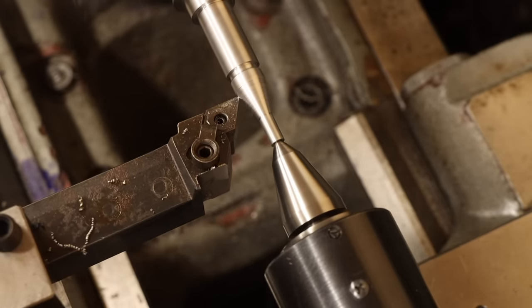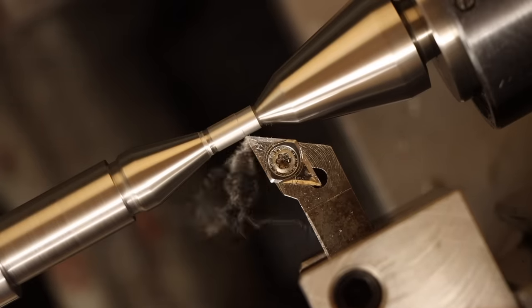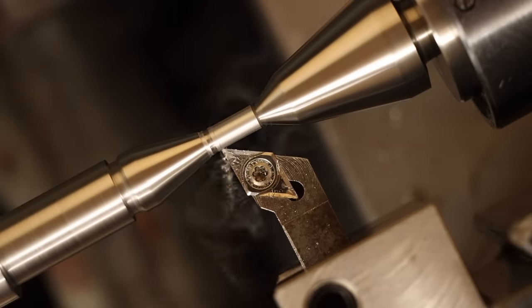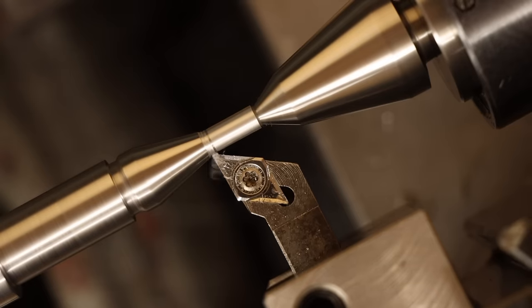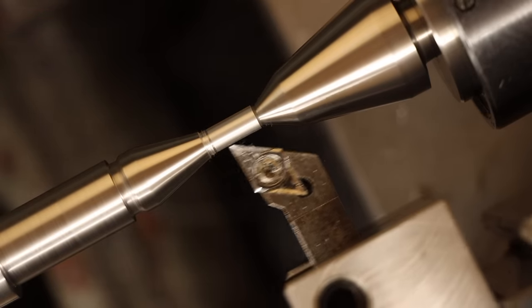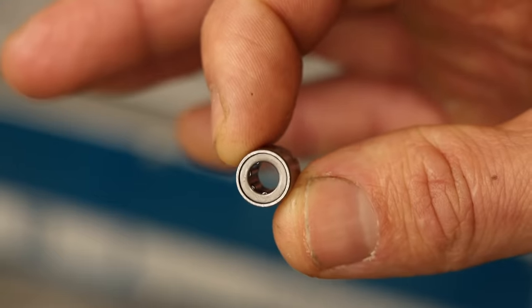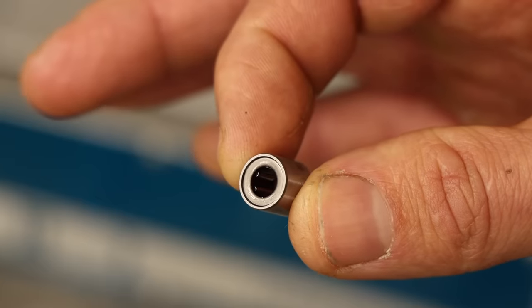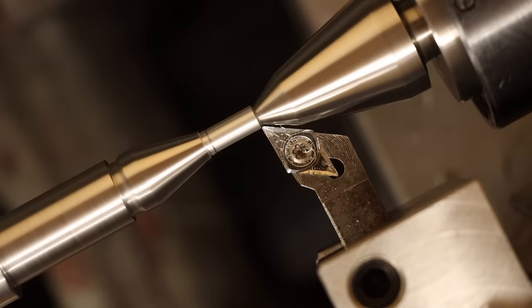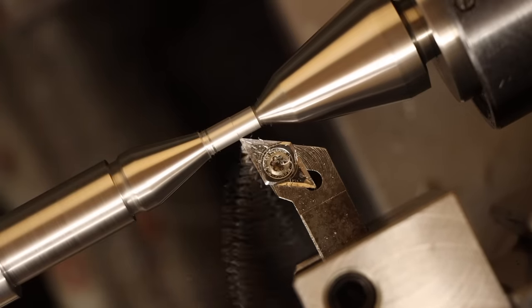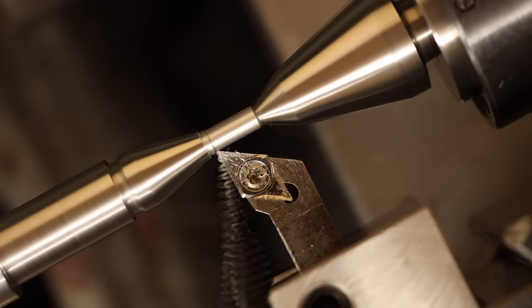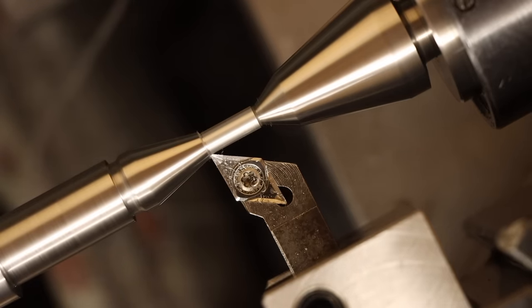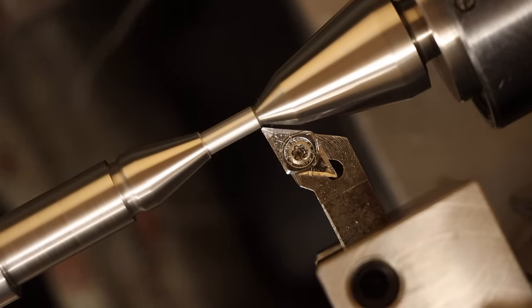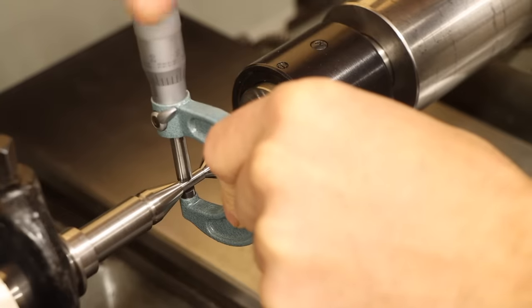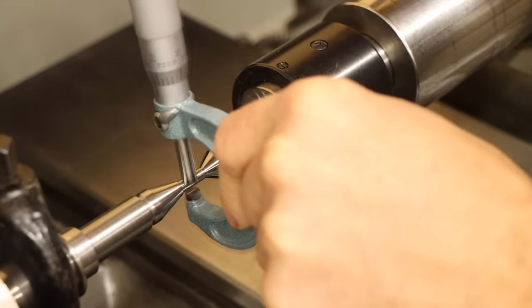Okay, I digress. One final diameter to take care of, and that's for the innermost needle bearing. Now, of all the things I'm concerned about with not hardening this part, this is probably the biggest. The needle rollers are going to be running directly on this surface, and this could go one of two ways. It could either wear out almost immediately, making this tool useless really fast, or the surface could work harden after just a few revolutions, and wear would stop in its tracks. Again, I don't have grinding equipment, so only one way to find out.